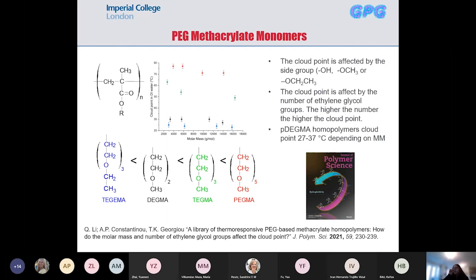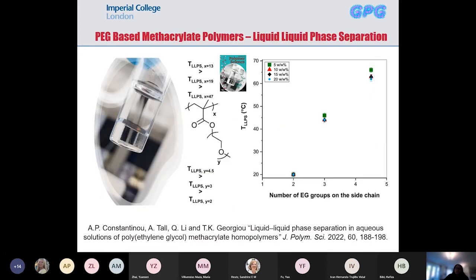So just to remind how the PEG methacrylate monomers can be thermoresponsive. Depending on the R, so depending on how lengthy the PEG side group is, and if the end group is going to be an ethyl or methyl group, the thermoresponsiveness changes. So the one that we have used, the DEGMA, that has only two groups of PEG, the cloud point was around 30 degrees. That, of course, goes down if you increase the molar mass. So this is the thermoresponsive group that was used in that patent. And if you also make a concentrated solution of these polymers and you heat them up, then you actually observe a phase separation. So you can have a liquid-liquid phase separation of these homopolymers.